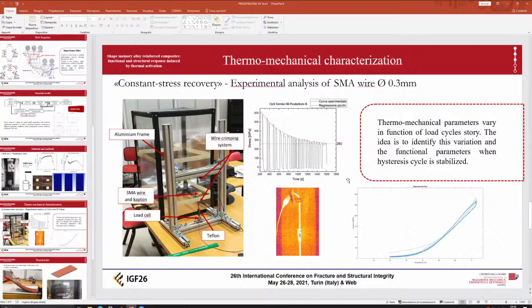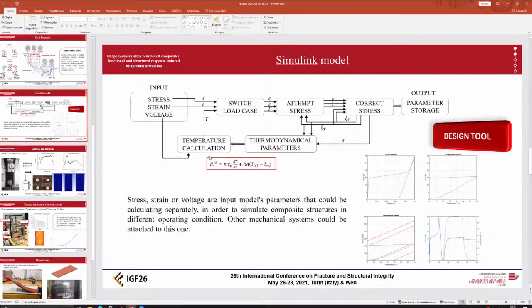With this model implemented in Simulink, we could use a sort of PID or a controller to realize a deformation controlling the current. Okay, understood. And about the modeling of this activation, are you able to also explain this degradation effect after all these cycles, or is it still the beginning of the work? We are still at the beginning. We can simulate the deformation and the stress applied on the wire or small element.